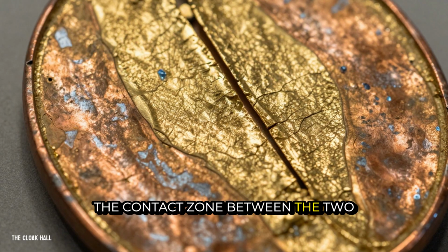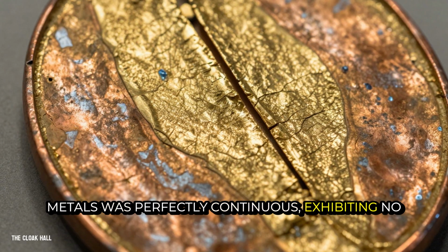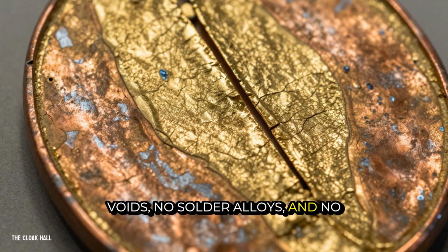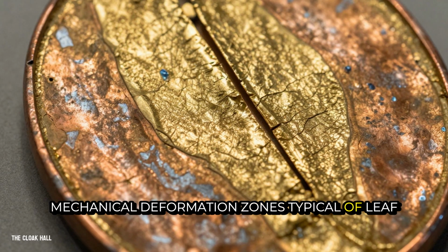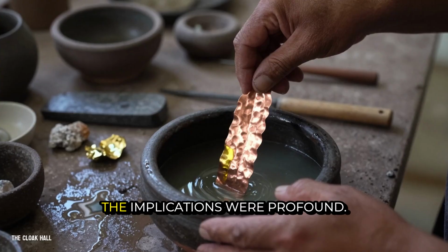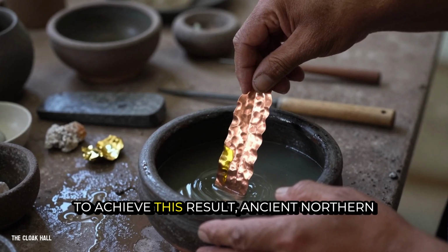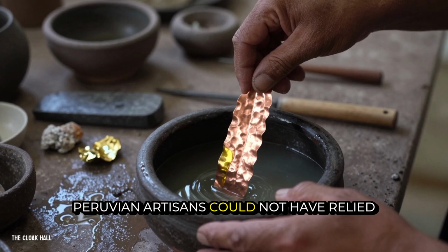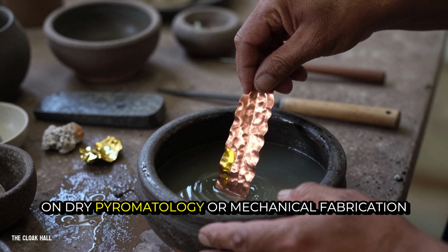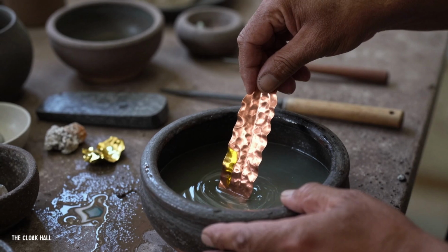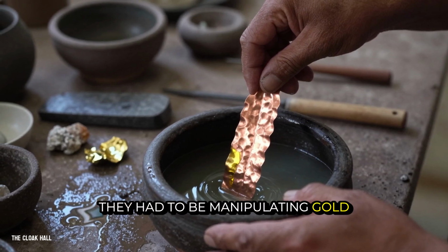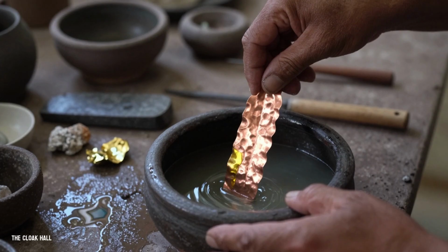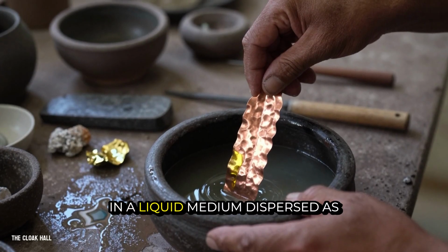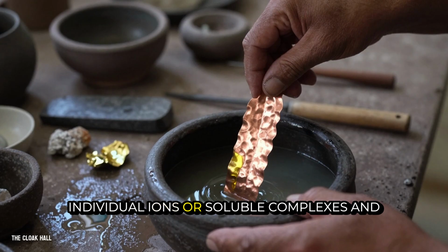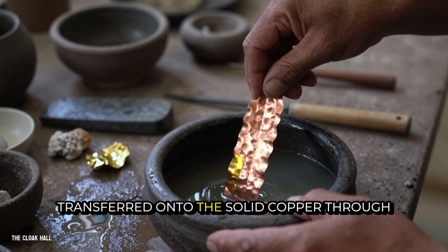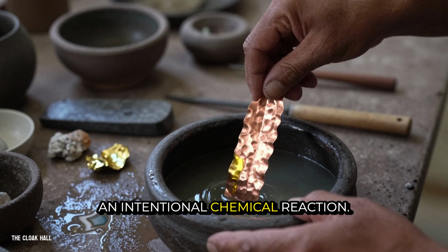The contact zone between the two metals was perfectly continuous, exhibiting no voids, no solder alloys, and no mechanical deformation zones typical of leaf gilding. The implications were profound. To achieve this result, ancient northern Peruvian artisans could not have relied on dry pyrometallurgy or mechanical fabrication alone. They had to be manipulating gold in an entirely different physical state. The metal had to be carried in a liquid medium, dispersed as individual ions or soluble complexes, and transferred onto the solid copper through an intentional chemical reaction.